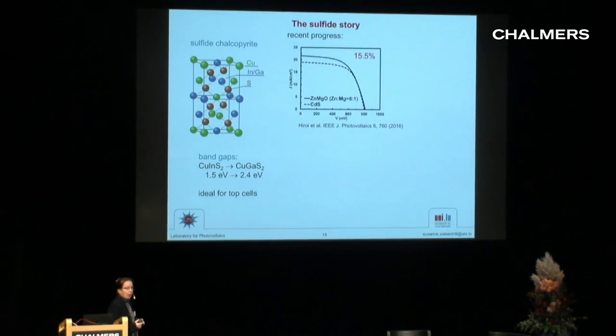And I would like to make another proposal. I showed you the copper indium gallium selenide. It has a band gap, as we usually use it, of around 1.1, similar to silicon. But this material has a cousin, the sulfide, copper indium gallium sulfide, which has the same chalcopyrite structure. And its band gaps vary from 1.5 electron volt to 2.4 electron volt. So they're exactly in the range that's interesting for top cells for tandem solar cells.